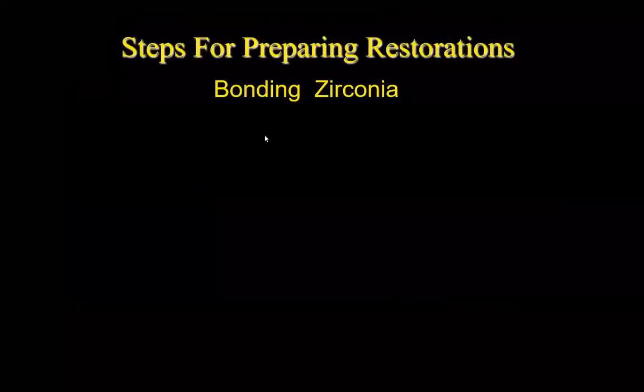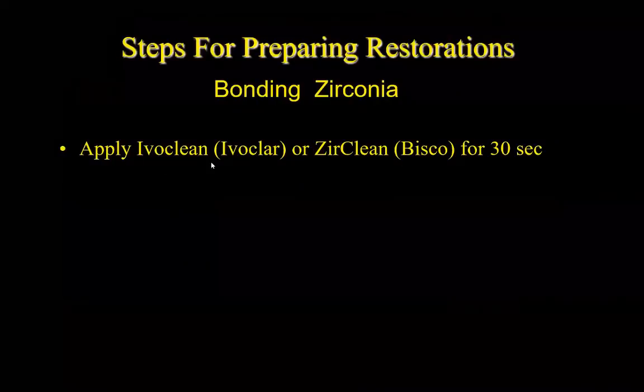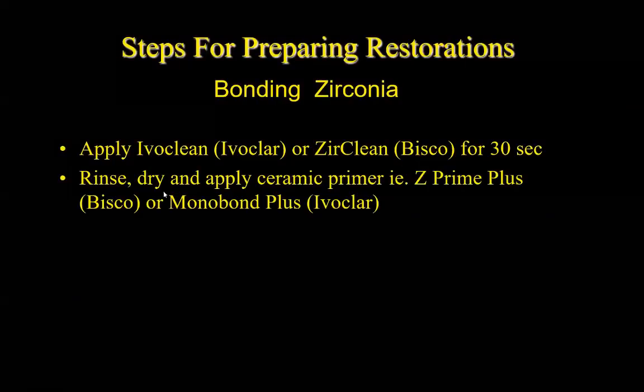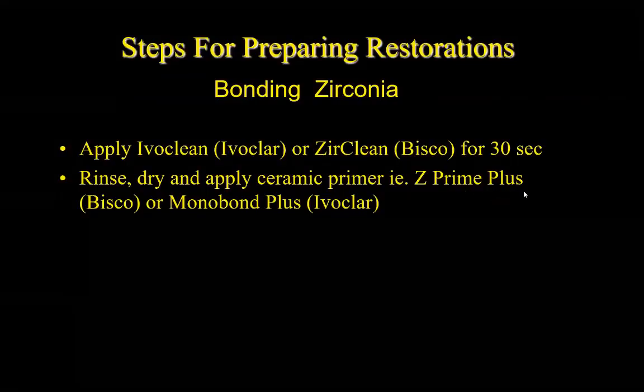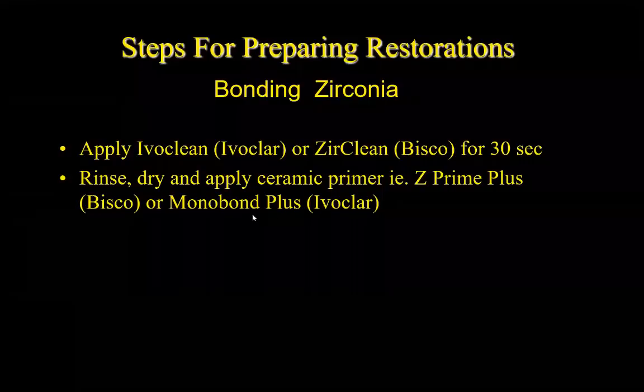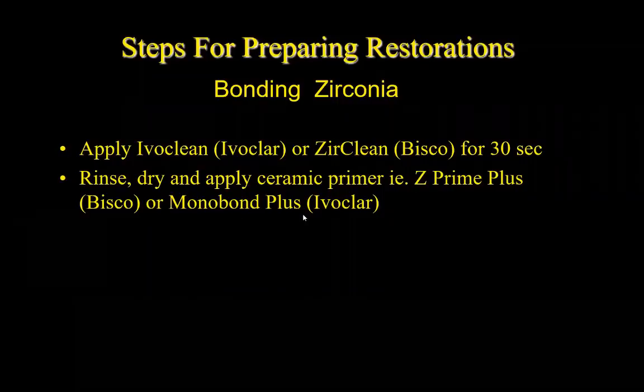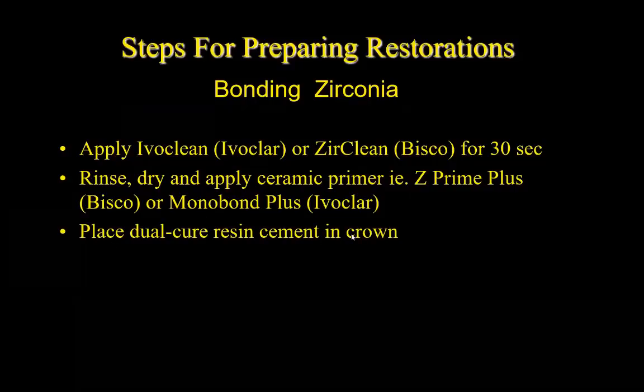The difference comes in how we prepare zirconia. We have to clean it with Ivoclean or ZirClean. We rinse, we dry. Now we're going to apply a different primer. It's not silane, it's Z Prime Plus, a zirconia ceramic primer, from Bisco, or Ivoclar's Monobond Plus. Remember, Monobond Plus can be used according to the manufacturer for either glass or zirconia because it contains silane in it, okay? We place our dual cure resin cement in the crown, okay?